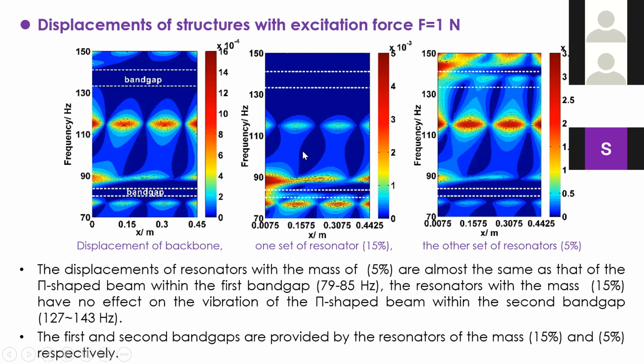This is the displacement of one set of resonators with a mass of about 15% of the backbone. And this is the displacement of the other set of resonators with a mass of about 5% of the backbone. We can see clearly that there are two band gaps in the backbone structure. At the first band gap frequency, the set of resonators with a mass of 15% of the backbone has very large vibration. By contrast, the other set of resonators, with about 5% of the backbone mass, doesn't vibrate at all in this frequency range. This means the first band gap is caused by this set of resonators.